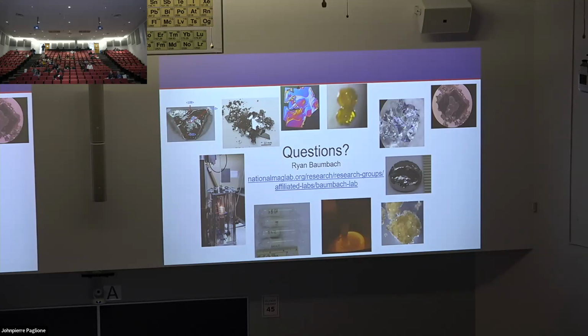It might be slightly technical or practical, but with the molten metal flux, recently I've been doing magnesium tin or, say, gallium cobalt tin. And sometimes when I was doing the flux method, when I was spinning it, I would still see some tin defects, like surplus tin in my sample. Is there any way that researchers can reduce surplus tin in this?